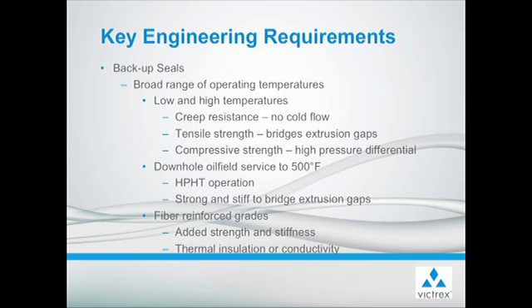Backup seals also need to operate in a broad range of operating temperatures and conditions, from low to high temperatures, requiring creep resistance or no cold flow, high tensile strength to bridge extrusion gaps, and high compressive strength to support high pressure differentials. Downhole oil field service at 500 Fahrenheit is typical for high pressure and high temperature operation, and the material still needs to be strong and stiff to bridge extrusion gaps. The use of fiber reinforced grades can add to the strength and stiffness of the material, as well as adding either thermal insulation or thermal conductivity if those are required.